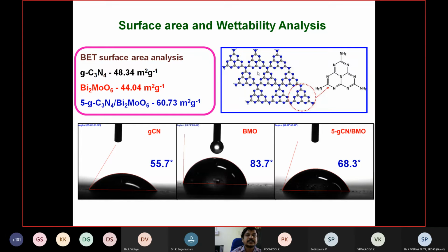We measured the surface area. The bare graphitic carbon nitride shows 48 square meters per gram. Likewise, the bismuth molybdate shows 44 square meters per gram. But once we make the hybrid material, the surface area is enhanced. Because in the synthesis we did ultrasonication, that leads to enhancing the surface area by making more exfoliation of this material.